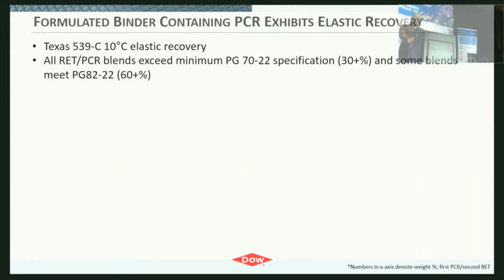So looking at elastic recovery, because we do want to show that there is elasticity here, what we found was in these formulation ranges that I shared earlier, we were able to easily meet the PG70-22 binder spec. The minimum requirement was 30%. Some blends were able to hit higher than 60% ER. Those would have met the PG82-22 for TxDOT.